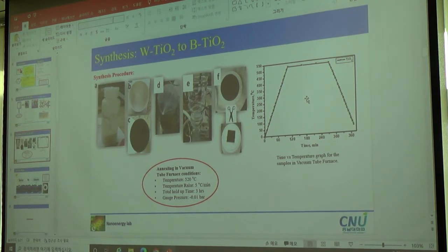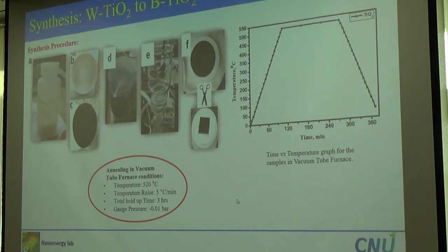And then after that, I made a concentration of 20 milligram per 100 milliliter solution in ethanol, and then I loaded it by vacuum deposition on the glass fiber filter, and then I cut it into 1.5 centimeters square for my STS experiment.